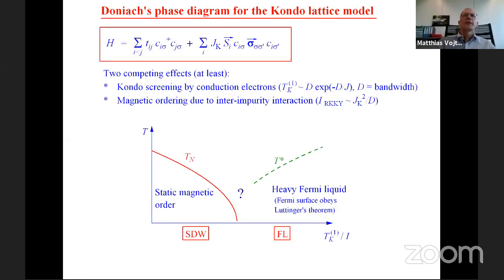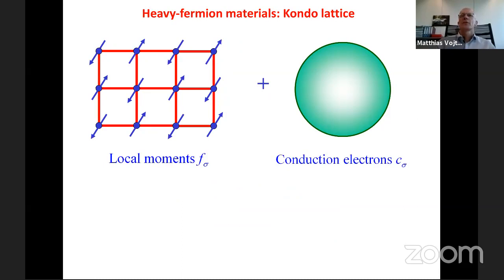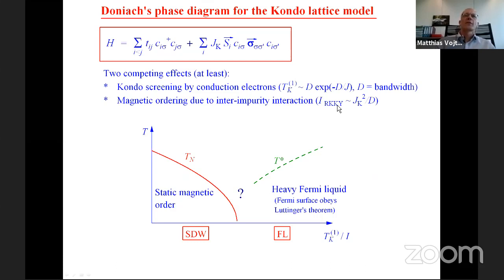If you think about this system here, then there are essentially two competing physics effects. One is that these local moments want to order. They can form an ordered magnetic state. And the other is that these conduction electrons can screen the local moments by the Kondo effect. This is physics which actually was realized already by Doniach in the 1970s, leading to a phase diagram as shown here. Here's temperature. Here's the ratio between these two effects, namely the ratio between the strength of Kondo screening, parameterized by a Kondo temperature T_K, and the strength of the inter-moment interactions. If the inter-moment interactions win, then there is static magnetic order. This you would call a spin density wave metal. And on the other side, the Kondo effect wins, and then you get a heavy Fermi liquid, which is non-magnetic.